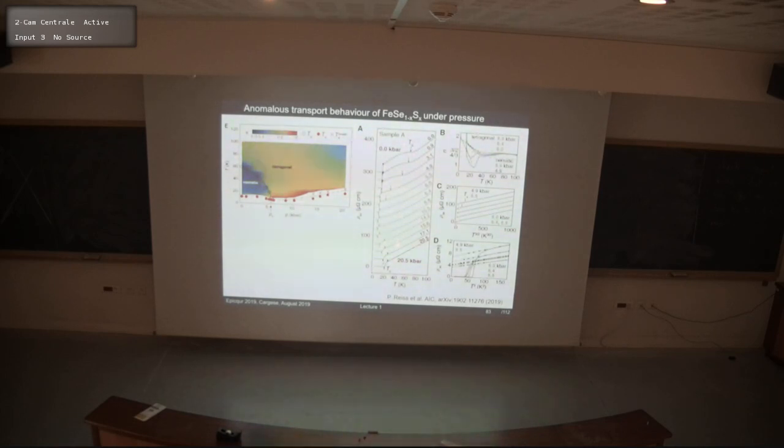And these are our resistivity data, again shifted for clarity. All these are the superconducting phases. And in this material, if we look just above the endpoint, there is no linear resistivity behavior. Instead, what we found is that just around this regime, the resistivity follows a 1.5 power law.